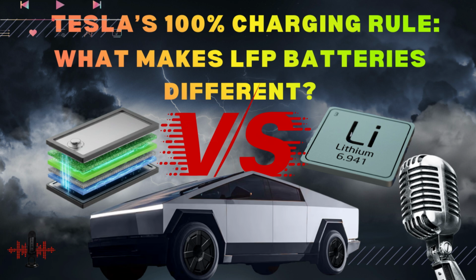Okay, so if the NCM battery is the high-performance, fragile sponge that tears and clogs itself up over 1,500 cycles, we now have to transition to LFP, lithium iron phosphate. This is where the durability numbers jump into a totally different league. What kind of lifespan are we talking about here? The durability leap is massive, and it's why this shift is so significant for the future of owning an EV. Where NCM typically maxes out between 1,000 to maybe 1,500 cycles, LFP chemistry has been rigorously demonstrated to maintain its capacity through an astonishing 3,000, 4,000, and sometimes even 6,000 full cycles.